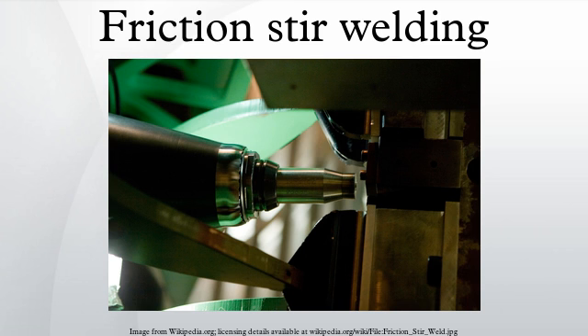This defect is particularly worrying since it is very difficult to detect using non-destructive methods such as X-ray or ultrasonic testing. If the pin is not long enough or the tool rises out of the plate, then the interface at the bottom of the weld may not be disrupted and forged by the tool, resulting in a lack of penetration defect. This is essentially a notch in the material which can be a potential source of fatigue cracks.